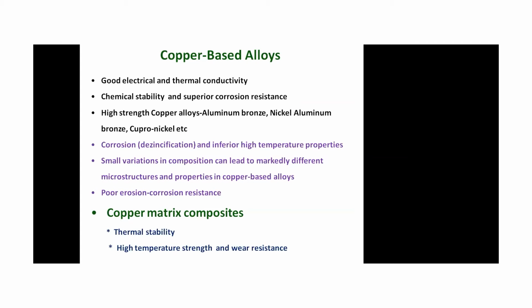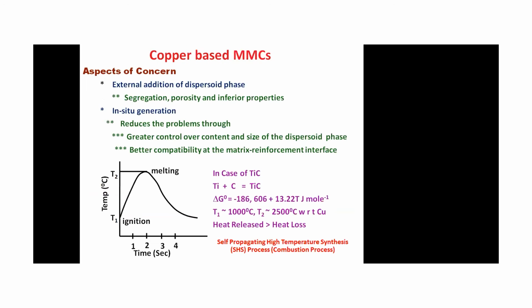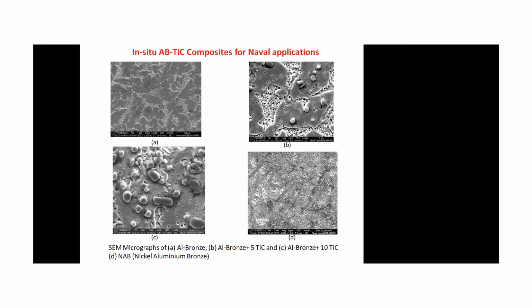For that, we have to add some kind of reinforcement into the copper. If we add any reinforcement into copper, two things will happen. One thing is thermal stability, because the expansion coefficient of any composite is almost lesser than the pure alloy, and it will also increase the high temperature strength, because ceramic particles have higher strength, and also increase the wear property. So we have added TiC as a reinforcement, and the TiC is generated by a chemical reaction. It has been added into the copper, and these are some of the micrographs. The conventional aluminum bronze, which is basically a copper, aluminum, and iron based alloy, is most commonly used.